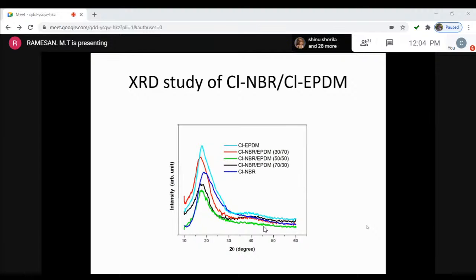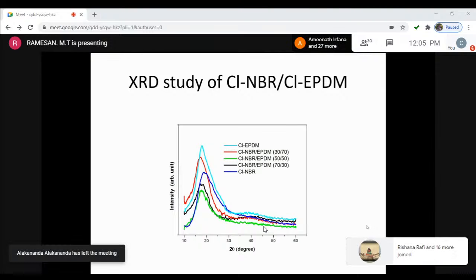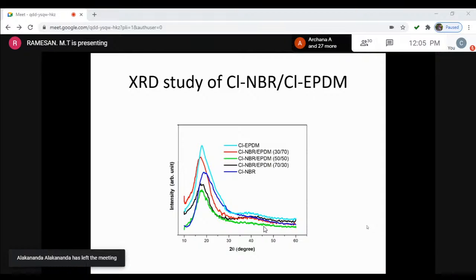Here you can see how the XRD gives an idea about this blend. You can clearly see that the chlorinated NBR, the blue color, has a broad XRD peak, and when we mix in this ratio, you can see in the green color 50-50 blend that the peak becomes too narrow. That means it gives some idea that the 50-50 blend may have good properties, and some vague idea about the mechanical properties can be obtained from this X-ray diffraction pattern.